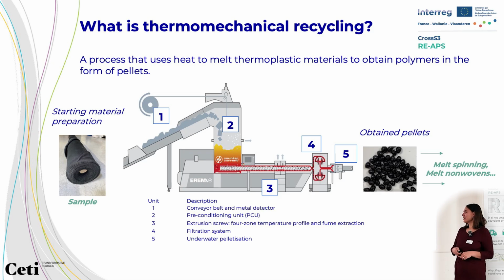Then we have unit 3, which is the extrusion screw, where we have 4 different temperatures that allow us to melt the polymer, and we have a fuming screw to remove compounds. We then have filtration screens where we can change the filter. And then we have an underwater pelletization unit, to obtain the pellets. This is an example of the pellets that we obtained from that starting fabric, which can then be used to make materials.